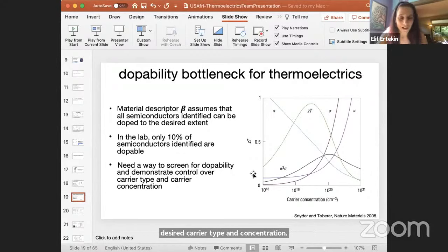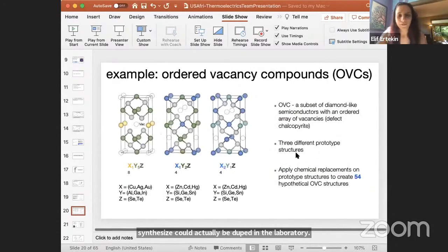But if you look at this diagram here, you see ZT plotted as a function of carrier concentration. It shows that in order to maximize ZT, we need large and controlled carrier concentrations approaching around 10^19 per centimeter cubed, which is quite large. Conversely, in reality, our experimental collaborators were finding that only around 10% of the materials they would try to synthesize could actually be doped in the laboratory. So there's a need to incorporate screening for dopability into our computation-guided search as well.